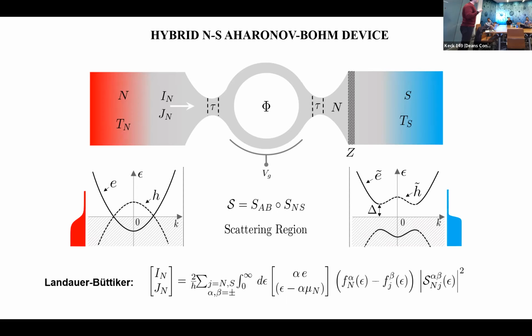And at this point, it's very important to notice that because we are dealing with superconductors, together with the presence of electrons, we have to take into account also the presence of holes. That's why here I represented in solid black lines the dispersion curves for electrons, and in the dashed lines, instead, the ones for holes, which are simply obtained by particle-hole symmetry with respect to the electrons. Notice also that in the case of the superconducting lead, the superconductivity indeed opens this gap in the dispersion relation curves, and this mixes electrons and holes, creating quasi-electrons and quasi-holes in the quasi-spectrum.